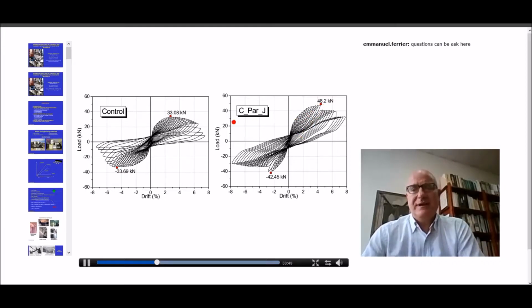So you can see that there is a clear increase in the capacity. The flexural strength before, that is the horizontal load, was 33 kilonewtons. It increases up to 48. So there is a substantial increase in flexural capacity. But then when our external reinforcement fails at this point, we have a reduction, which could be gradual depending on how exactly those externally applied fibers would fracture.